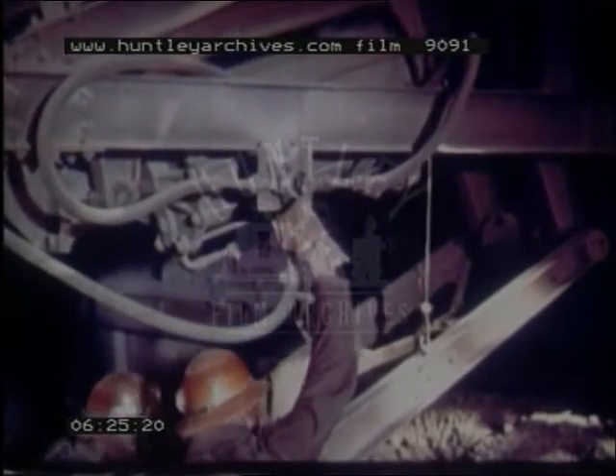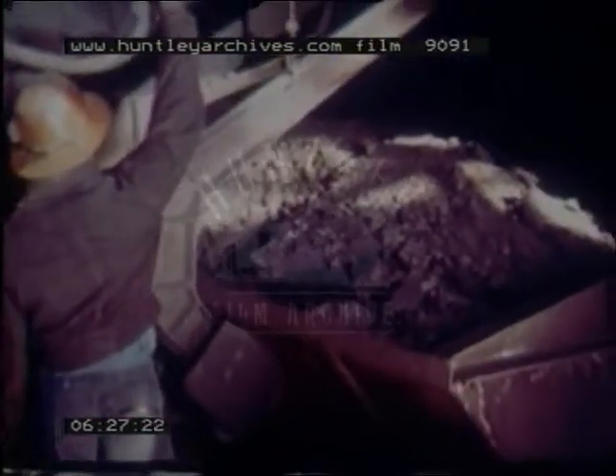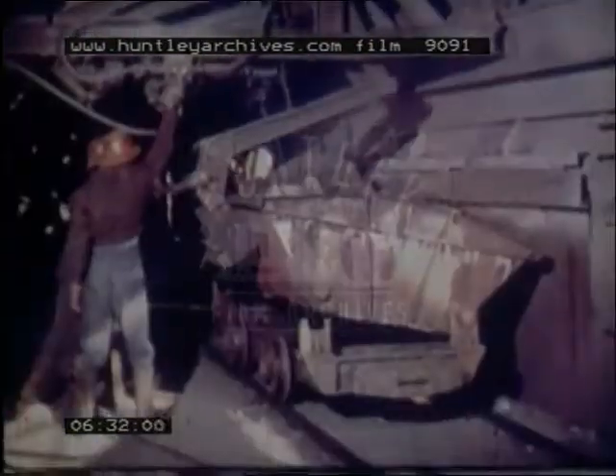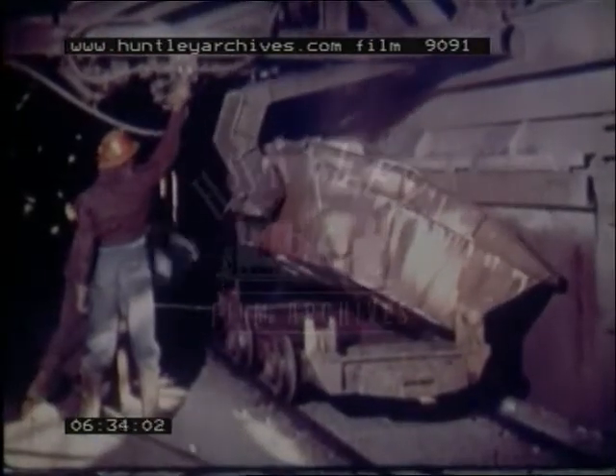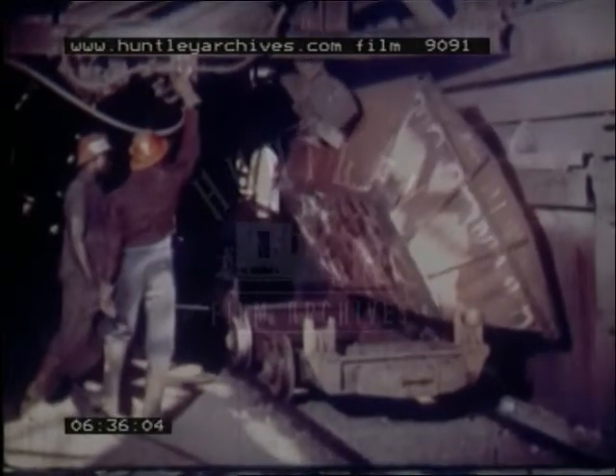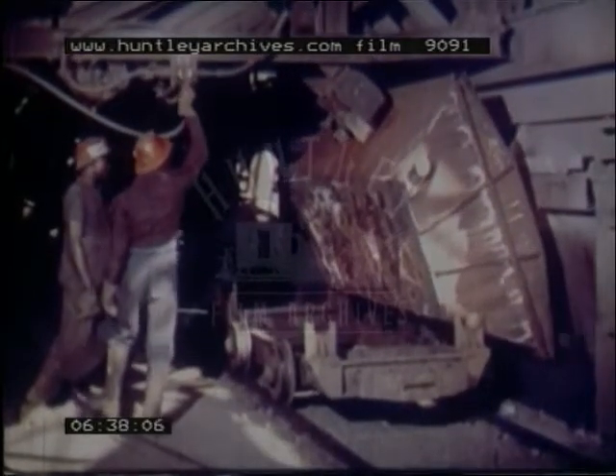At a temperature of 1300 degrees centigrade, the impurities will combine to form a fluid slag which floats on the surface. Underneath the slag is found the metallic part, the matte, a mixture of metallic sulfides with a high copper content. Air necessary for fusion is injected through air nozzles called tuyères. From time to time, they have to be unclogged with a steel rod.